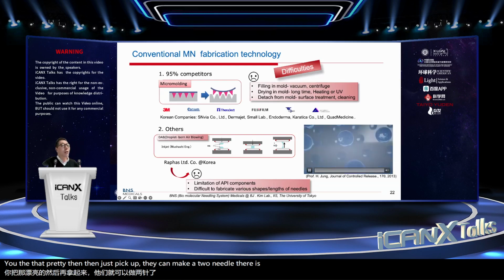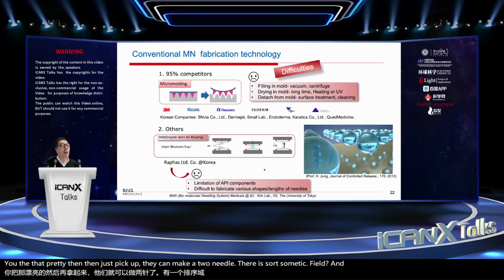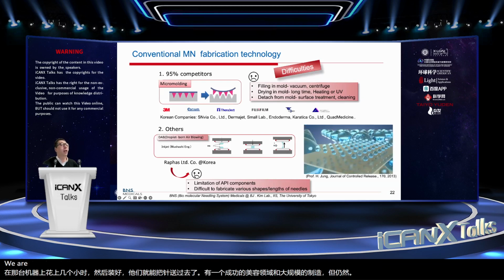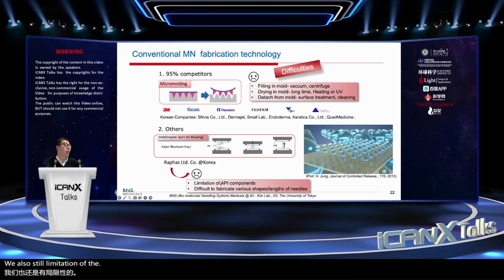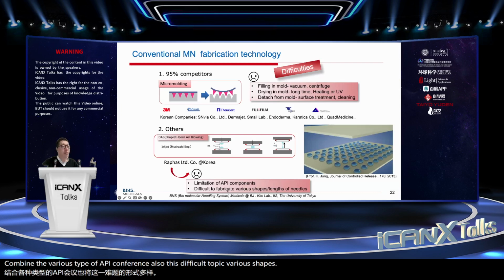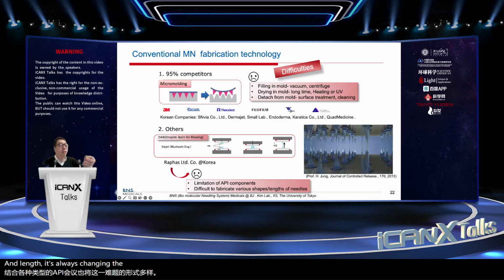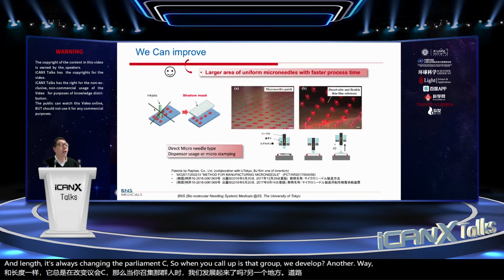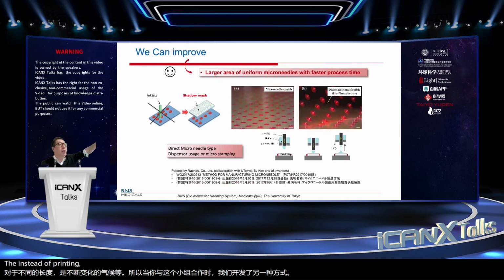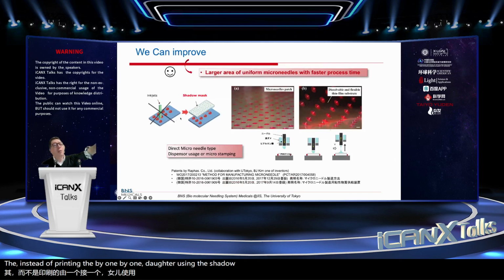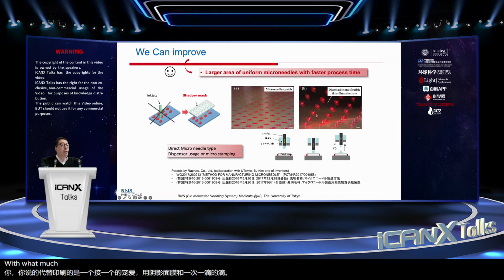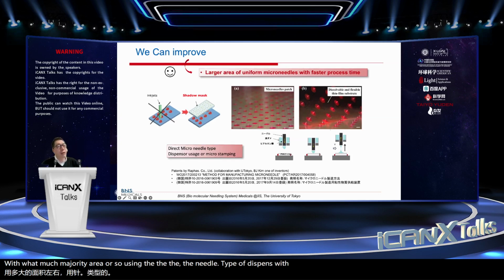There is success in the cosmetic field and mass fabrication, but that way still has a limitation in combining various types of API components. Also, it is difficult to fabricate various shapes or various lengths. It always requires changing parameters, etc. So when we collaborated with that group, we developed another way: instead of inkjet printing one dot at a time, we use a shadow mask and one-time droplet over a much larger area. Or using a needle-type dispenser, we directly pattern the needle, etc.